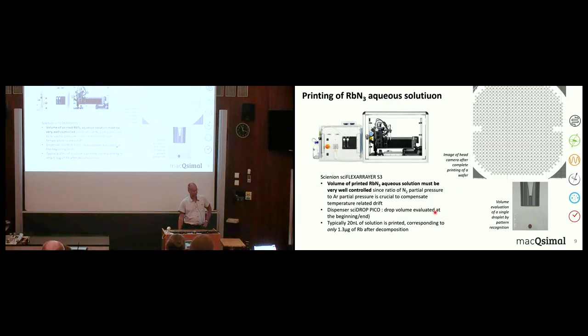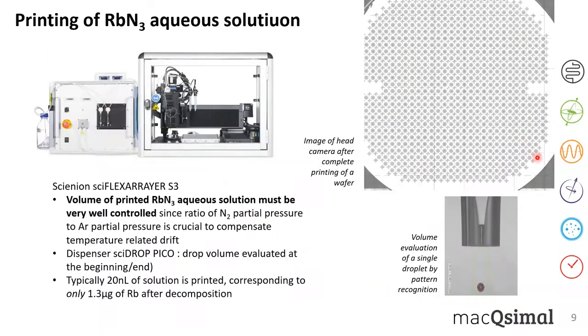There's also a picture that is taken for every cavity that is filled. You see this here. So in this case, we made the same filling for all cells, but of course we can also vary it, and we did this also, so that we have zones of the wafer where we fill with less or with more rubidium azide. But typically we use 20 nanoliter of solution that we print into each cavity, and this corresponds, after decomposition of the rubidium azide, to roughly 1.3 microgram of rubidium in each cavity.